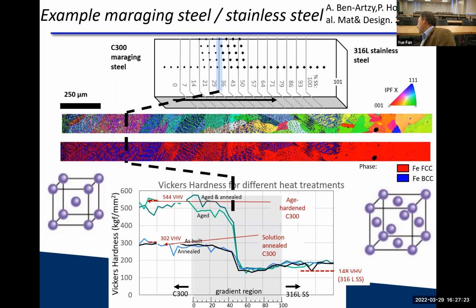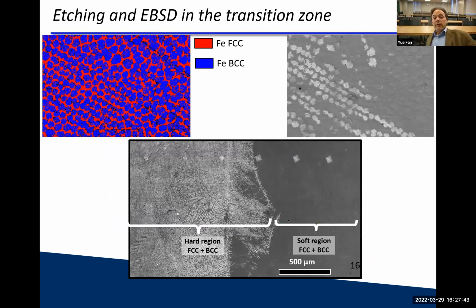And of course, it's heat treatable maraging steel. So when you heat treat it, it pops up quite a bit in hardness to an aged version. And so that's what we end up with here. Now, that's interesting. Why do you see a gradual change in the phases, but not a gradual change in the hardness at all? When we etch these microstructures, again, here's this FCC BCC mixture. This microsegregation is causing the slight difference between FCC and BCC. But only some of them etch, as you can see, and some of them don't. Not all of them etch at the same rate. And when you then do a hardness test, you can see this is the soft region, large imprint, hard region, small imprint. So where it etches, it's harder than where it doesn't etch, for some reason.